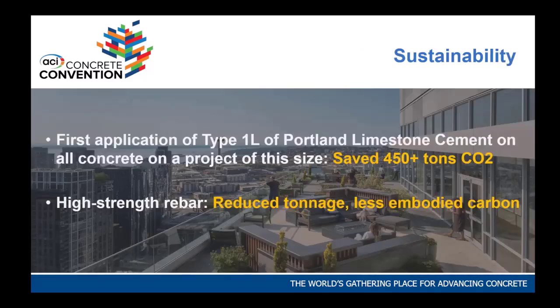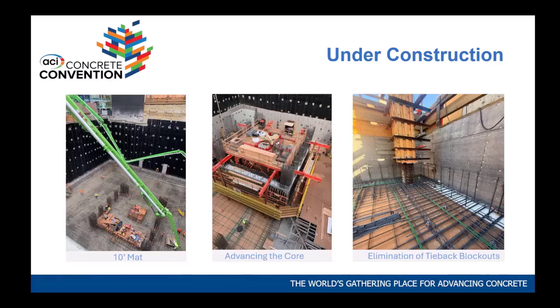So embodied carbon was an interesting thing on this. Let me just go back here too. One of the things we used is grade 80 steel throughout the foundation and throughout the boundary elements of the core walls, because there's a lot of tension involved. And then the confining steel was grade 80 steel to reduce the amount of confinement.